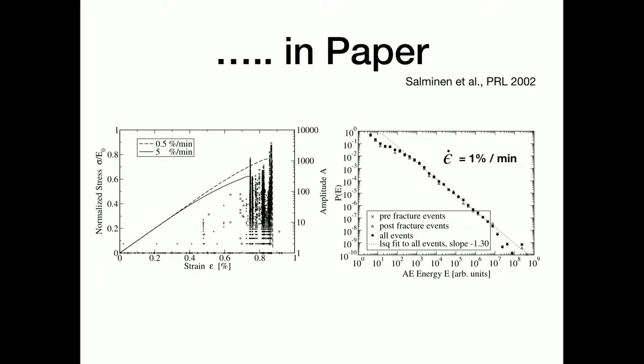And here it's actually newsprint paper, in which a small notch is put, and then it is subjected to an opening mode, which doesn't really remain opening mode because the paper deforms out of plane also. But what is measured is again the acoustic activity at 2 different strain rates or loading rates in the remote displacement. And what is seen is that at a higher rate the fracture initiates, and this is the force deflection curve hidden behind the acoustic signals. So you have acoustic activity prior to this, and you have it post that also.